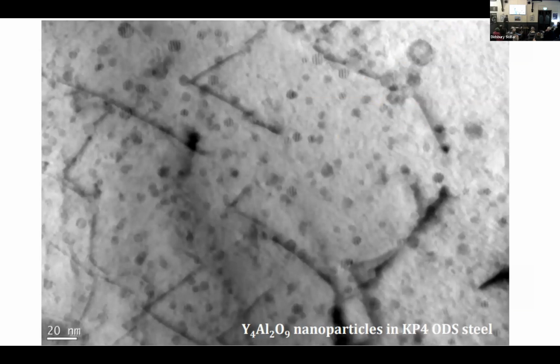Another idea is what we call oxide strengthened steel, where we put, if you can see these tiny little black dots, these are literal nanoparticles. These are about 100 atoms across, and we've put these tiny little particles in there. And the idea is that these particles will suck up the defects that we're putting in with the irradiation, and this will improve its tolerance for radiation as well.